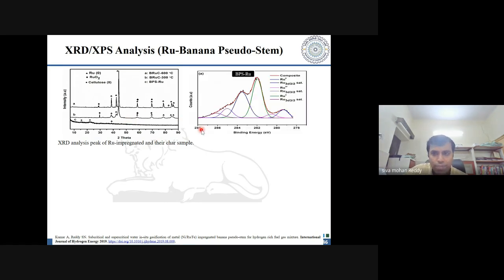And whereas you see that at 300 degrees centigrade, the ruthenium existed in the form of ruthenium oxide. Then if you look at the XPS, we made sure that we deconvoluted the composite red curve that it has formed. You see the blue one at a binding energy of 277.7 electron volts. We see that the ruthenium existed in the form of actual metal, active ruthenium, with the corresponding satellite peaks at 3d 3/2, and